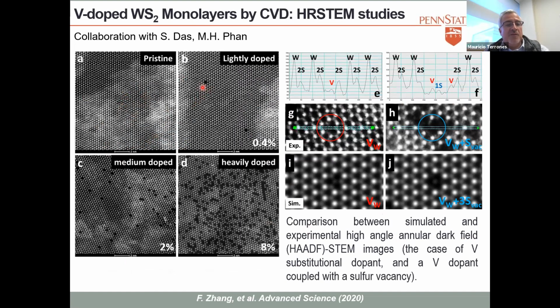This is when we have 0.4 atomic percent of vanadium. So they look like vacancies, but they are not vacancies. There's an atom in between in there. And then you have 2% or 8%. So 8% it's quite a bit, right?